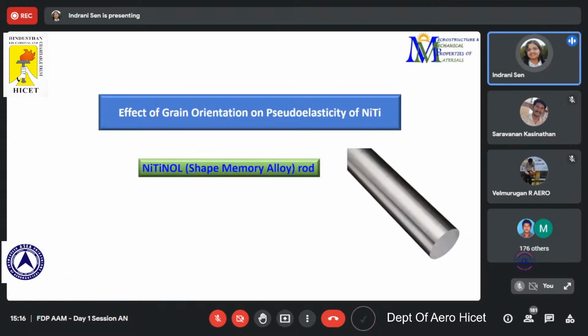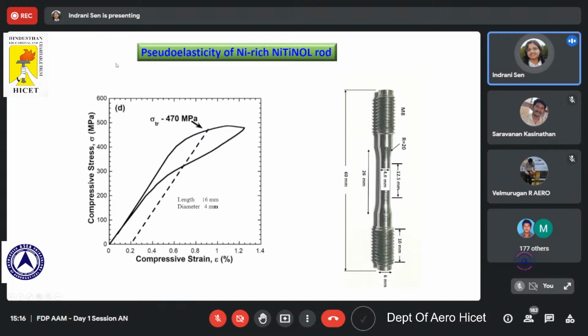Now, let's come to some of the experimental results. What we have seen in this study is very interesting. We have a nickel titanium rod, something like this, of around 10 millimeter diameter, and it shows very good elasticity in a tensile sample as per the standard. And when we tested this, you can see that this one is the compressive stress strain diagram, but you can see that it can undergo the phase transformation, and once the load is removed, whatever strain has been generated is completely recovered.